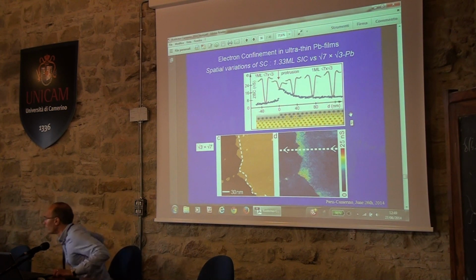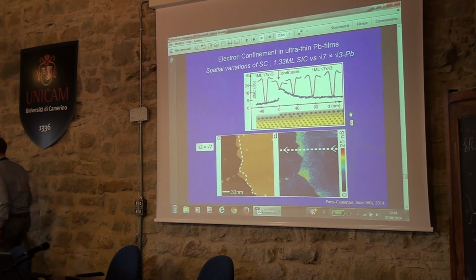Yes, please. You can see, for instance, here we plot the density of states as a function of position. And you have a jump of the density of states, a jump at the atomic scale when you move from one terrace to another. It means that you have a jump in the order parameter. And for us, a jump in the order parameter, which is a continuous wave function, is only possible if you have a barrier. So it means that the single atomic step in this material is a real barrier for Cooper pairs. And it means that it is really a Josephson junction, and the superconductivity is really confined to the very topmost atomic layer. Okay, any other questions?